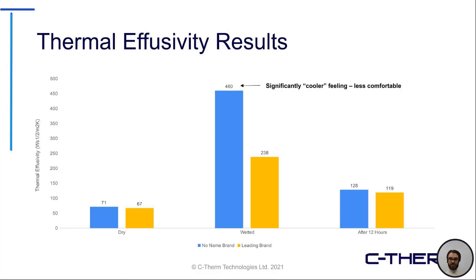But when you initially wet the material, so when it becomes saturated, I call it that time equals 0 condition, and it's measured, the no-name brand sample had a much higher effusivity measurement, most likely related to the top sheet and surge layer not being able to adequately disperse that liquid through the material of the diaper, and there's more of that cool feel at the skin of the baby there.